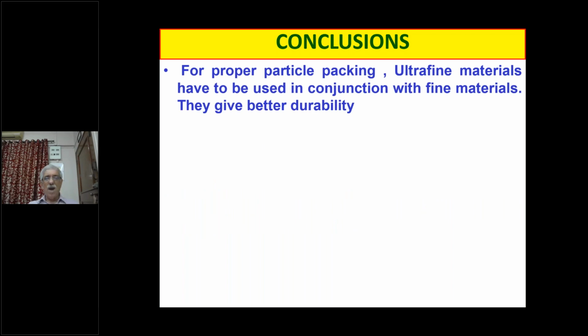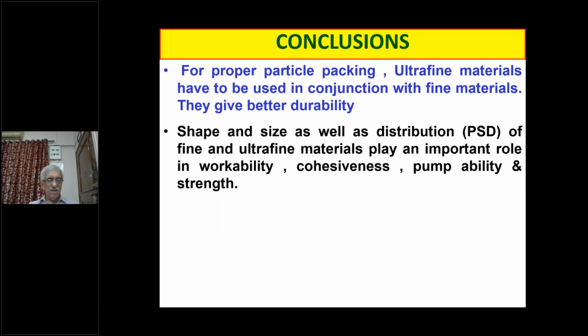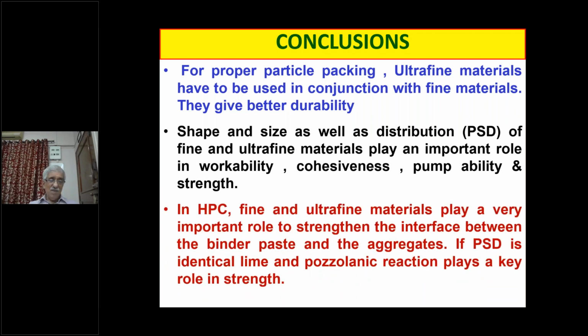For proper particle packing, ultrafine material has to be used in conjunction with fine material. They give better durability. Shape, size and particle size distribution of the fine and ultrafine material play an important role in workability, cohesiveness, pumpability, flowability, and strength. In high performance concrete, fine and ultrafine material play a very important role in strengthening of the interface between the binder paste and the aggregate. If particle size distribution is identical, lime and pozzolanic reactions play a key role in strength. So this point is to be borne in mind.